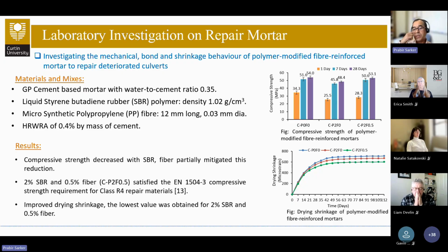From many trials, the results of compressive strength are presented on the right hand side, and the shrinkage behavior of the mortars is presented in the diagram at the bottom. What was found was that with the SBR polymer, compressive strength actually went down, but that was partially mitigated by the synthetic fiber.